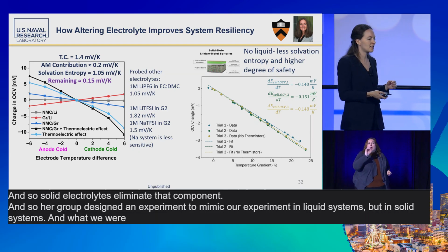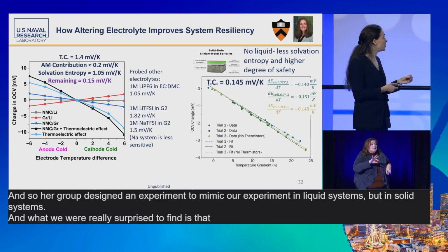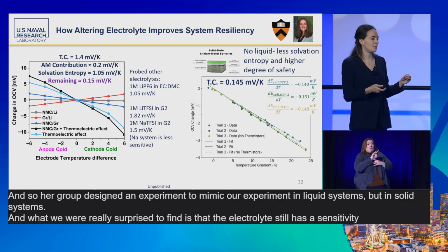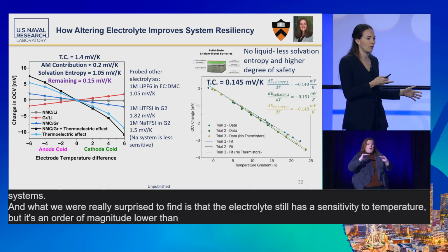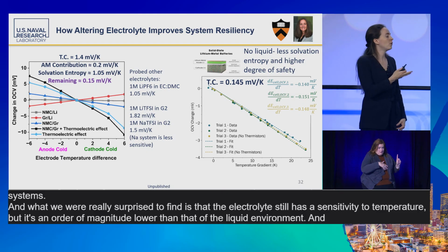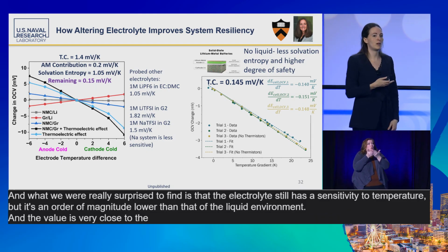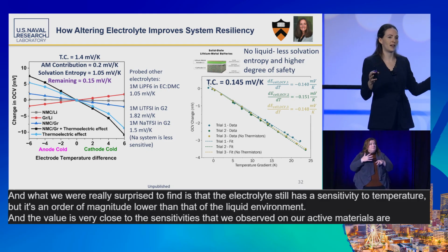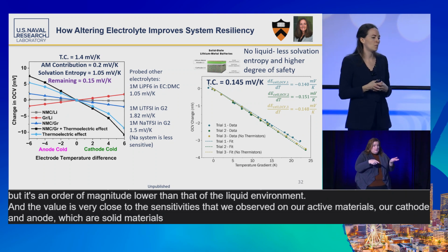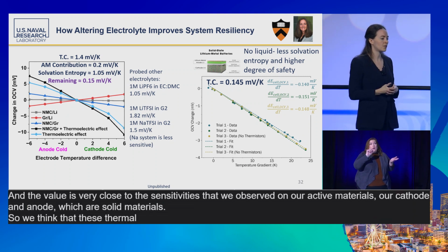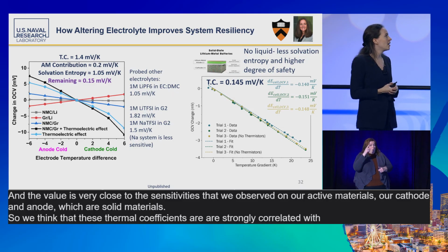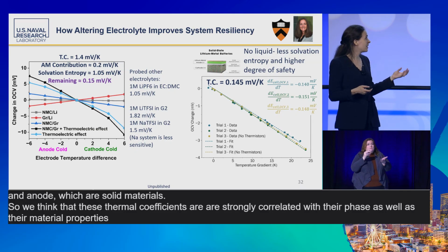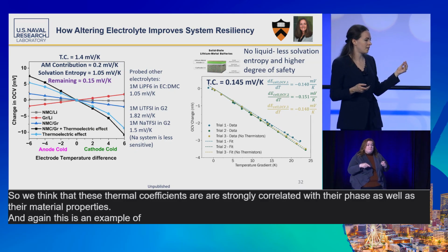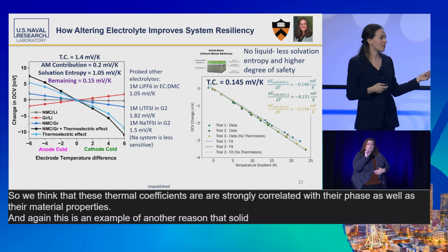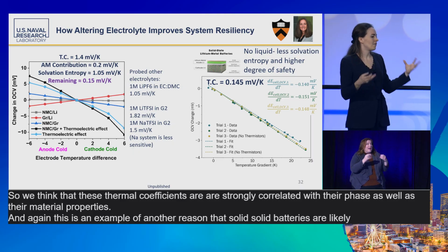And what we were really surprised to find is that the electrolyte still has a sensitivity to temperature, but it's an order of magnitude lower than that of the liquid environment. And the value is very close to the sensitivities that we observed on our active materials, our cathode and our anode, which are solid materials. So we think that these thermal coefficients are strongly correlated with their phase as well as their material properties. And again, this is an example of another reason that solid batteries are likely safer, because they have this resilience to temperature.